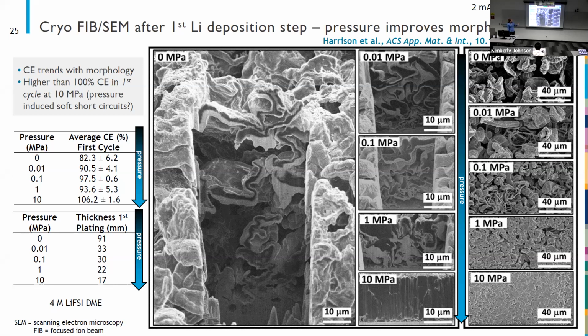So you can see that the morphology expands a lot when we go to lower pressures, and we're able to get much denser morphology at higher pressure. That correlates pretty well with first cycle Coulombic efficiency as well. And we see that at 10 megapascals, the Coulombic efficiency in every replicate we've tested is over 100%. That's a problem. That means we likely are forming short circuits even on our very first deposition and stripping cycle.